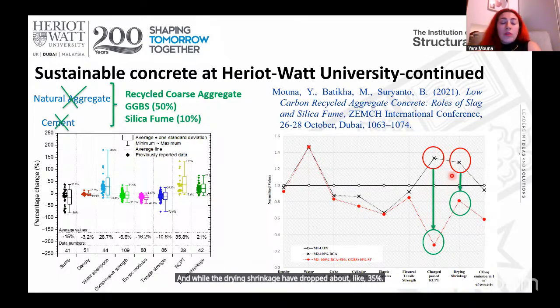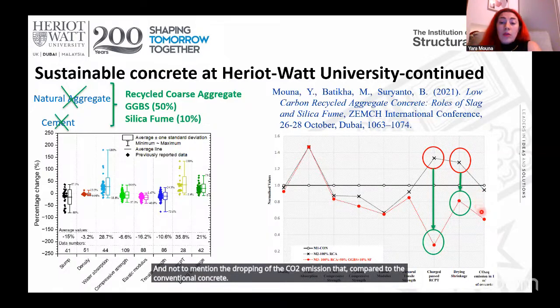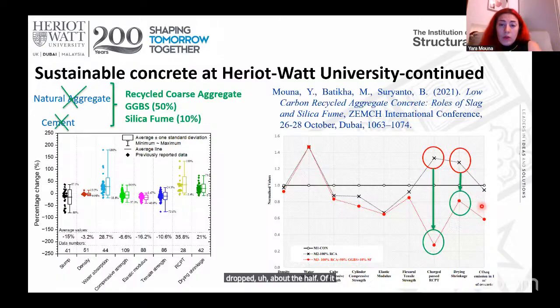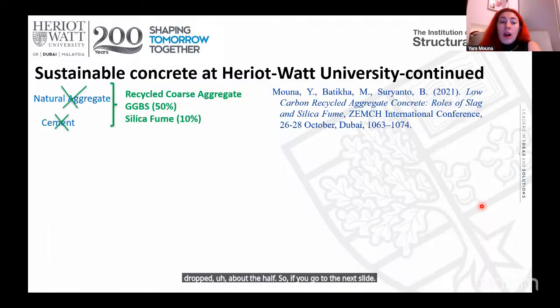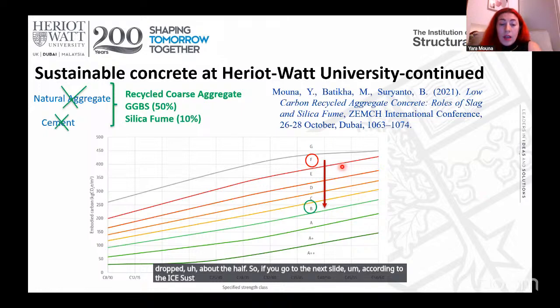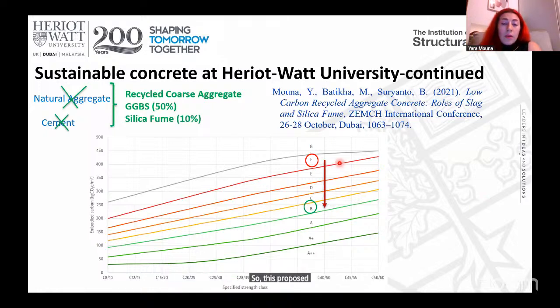And not to mention the drop in CO2 emission, which, compared to the conventional concrete, dropped to about half. So if you go to the next slide, according to the ICE sustainability grades, this proposed concrete mix was able to improve the sustainability grade of the concrete from F, the worst, way into the green part of it. This is the B level. And this gives this mix good potential for further research, and this is what we've done.